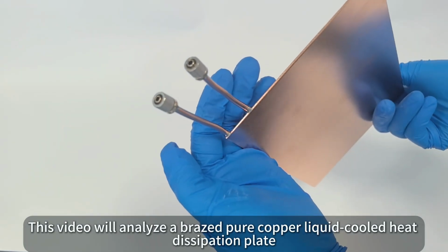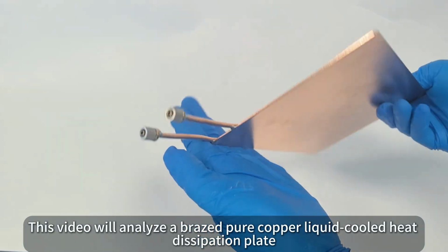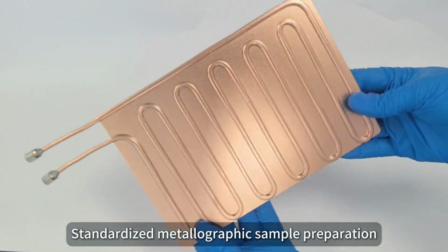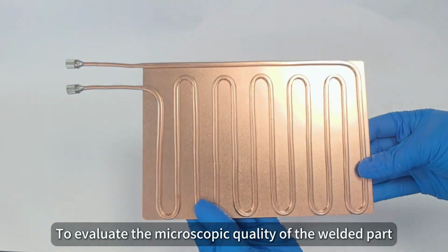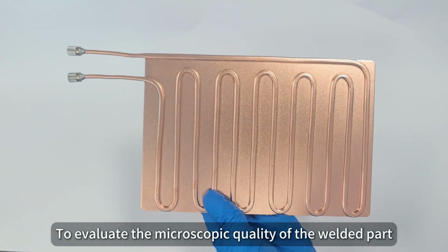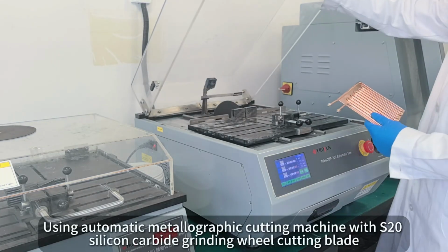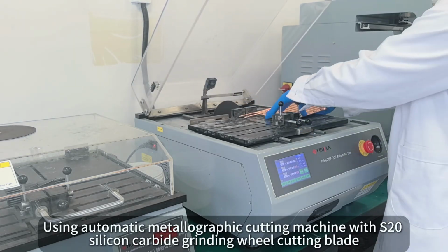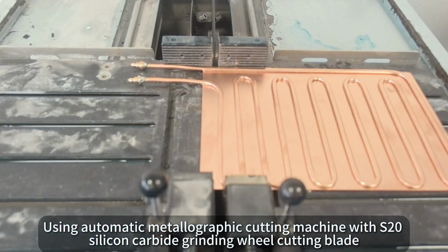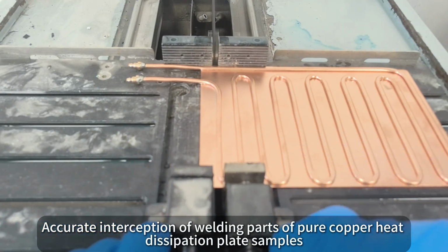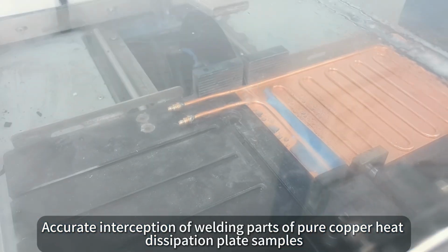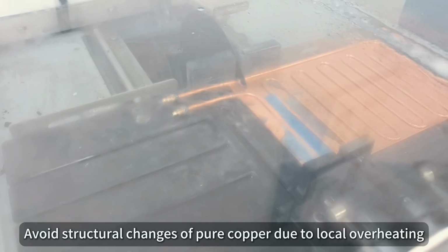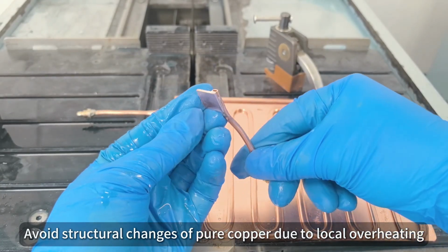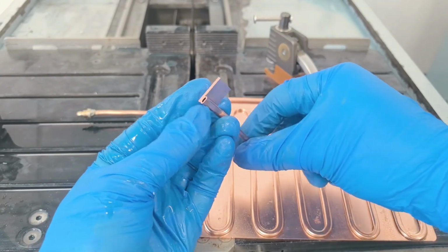This video will analyze a brazed pure copper liquid-cooled heat dissipation plate, using standardized metallographic sample preparation to evaluate the microscopic quality of the welded part. Cutting. We cut and sample using an automatic metallographic cutting machine with an S20 silicon carbide grinding wheel cutting blade, accurately intercepting the welding parts of the pure copper heat dissipation plate samples. Adequate cooling is required during cutting to avoid structural changes of pure copper due to local overheating or thermal damage to brazed joints.